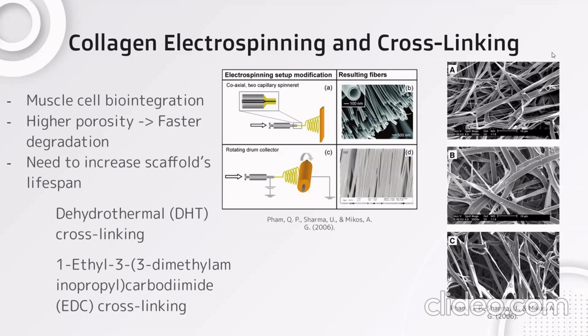On the topic of biointegration, however, the higher the porosity of the mesh, so basically the porosity of the fibers themselves or the distance between the fibers, the faster the degradation of the implant. However, also the higher degree of biointegration the implant demonstrates. So you need to find a balance between the lifespan, the degradation speed of the implant, and the biointegration of the implant, like how well it biointegrates with cells.